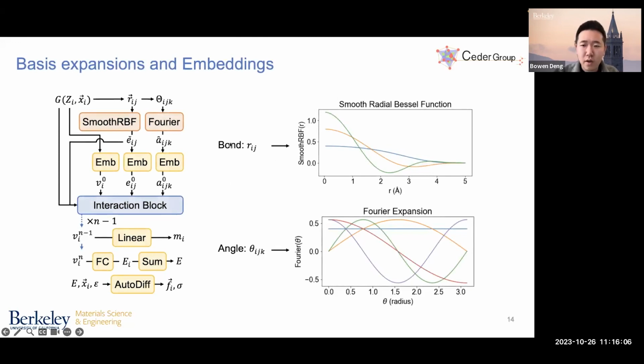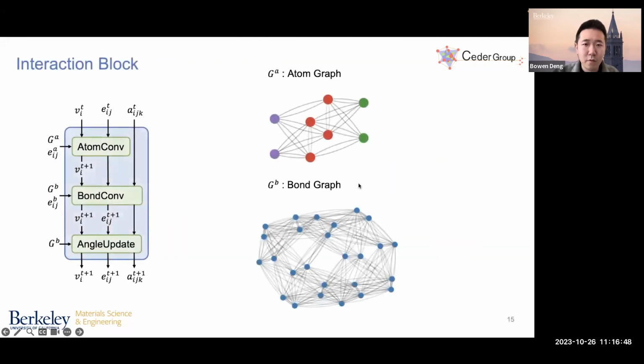After we have constructed this atom graph and bond graph, we pass them into these deep learning models, where at the first step, we basis expand this bond and angle information, and in machine learning language, we embed them into high-dimensional hidden vectors. The bond distances are expanded by smooth radial Bessel functions, and the angle information is expanded by Fourier expansions. After these embedding layers, which I show in the yellow color blocks here, these high-dimensional vectors are updated through these interaction blocks, where we simulate the information transfer between the atoms. The interaction blocks contain essentially 3 layers, where we iteratively update the atom, bond, and angle features that are predefined by the pairwise relationship in the atom graph and the bond graph.